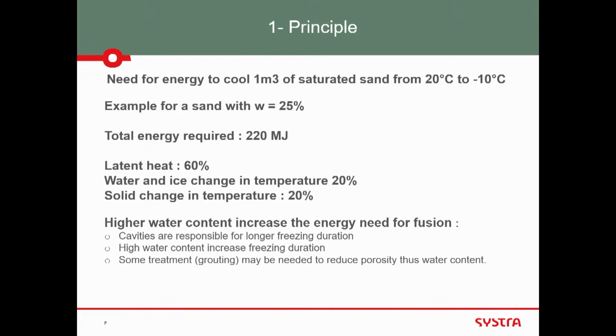So the remaining is the change of temperature of the soil structure. Here it's sand particle. You take the sand particle from +20 to -10. It represents 20% of the energy, roughly. So if you don't want to bother, just compute what is the water content. Easy. And then plus 20%, that's all. But what also is very important is that energy is dictated by water content. Low water content, lower energy; high water content, a lot of energy. And in this case, the part of the solid change in temperature is smaller. So the more water content, the more energy goes into the water; the less water content, the more it goes into the soil particles. This is very important.